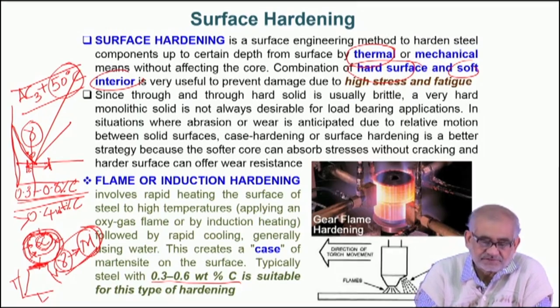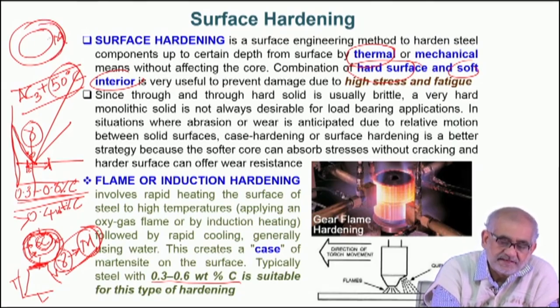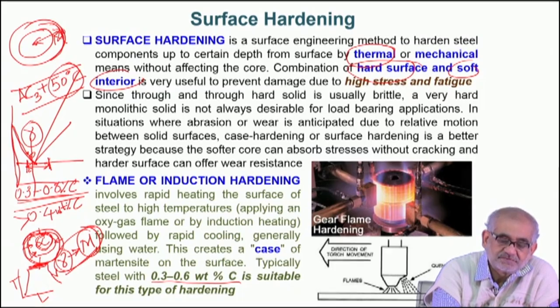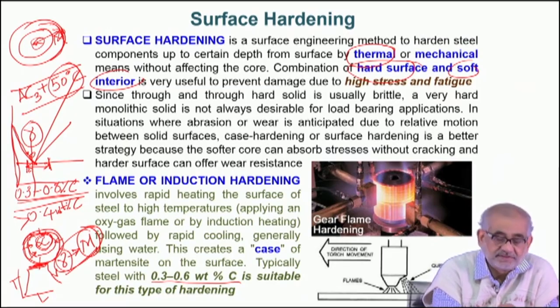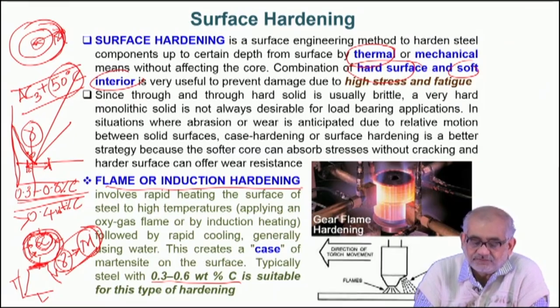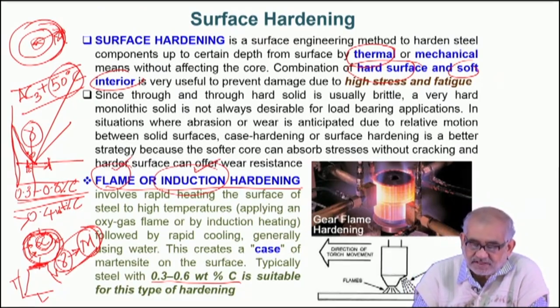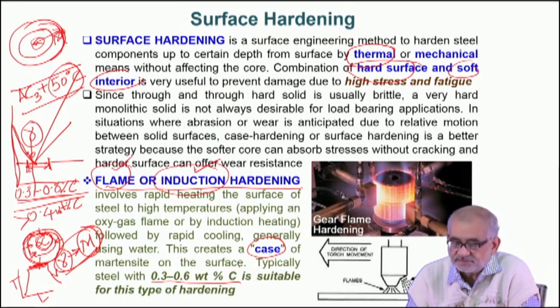It is important that we create a graded microstructure. In the cross section, we want a gradation from fine acicular martensite at the surface to a polygonal ferritic or ferrito-pearlitic microstructure in the core. In the process, we see a gradation from pure martensite to martensite plus ferrite-pearlite combination. This is achieved through thermal activation by either flame hardening or induction hardening. The hard surface layer created is called the case, and the case depth can be a millimeter or less, or even a few millimeters in some cases.